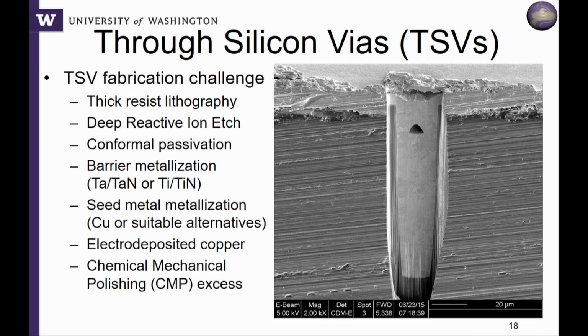In order to get metal down those holes, if we use really big holes, we can use traditional things like sputtering, where we just shoot metal ions everywhere and they eventually coat the sidewalls, and then we can do electroplating. The problem is we want a lot of connectivity, so we can't live with a 100 micron diameter hole. People are pushing us to be at like 2 to 5 microns. And as you shrink things down to 5 micron diameters while still being 150 microns deep, getting metal down a very narrow hole or pore becomes a substantial challenge.